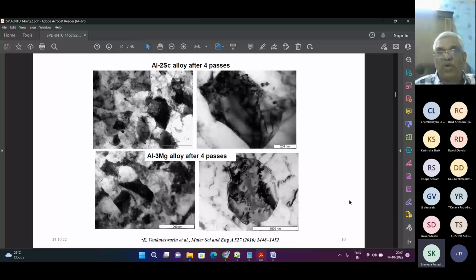So that sample itself we have taken and tried the ECAP process, and after 4 passes we can see that the grain size is drastically reduced. At higher magnification you can see that the grain size is still reduced, almost 200 nanometers. So the grain size has been drastically reduced. And similarly, we have done it with the aluminum-magnesium alloy after 4 passes.